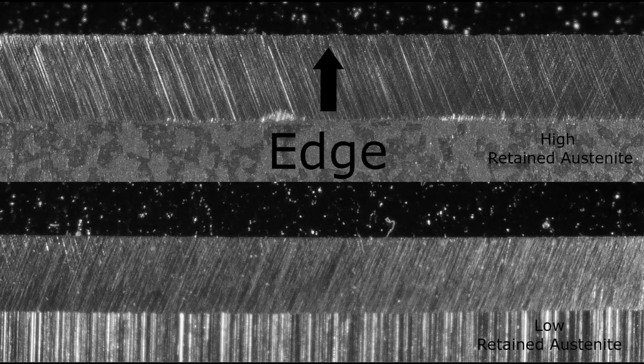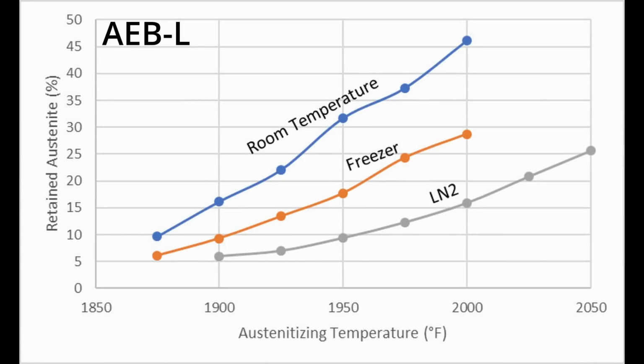Retained austenite can be minimized in different ways. If you austenitize at too high of a temperature, that increases your retained austenite. When you do that in combination with a slow quench speed, and if you skip cryo, then definitely you get excess retained austenite. Both small batch heat treating and commercial heat treaters can have issues with retained austenite. But there are a couple areas where commercial heat treaters are at a disadvantage. One is the slower cooling rate that we've been discussing all throughout this article. Slower cooling stabilizes retained austenite, which makes less of it transform during a cold or cryo treatment.